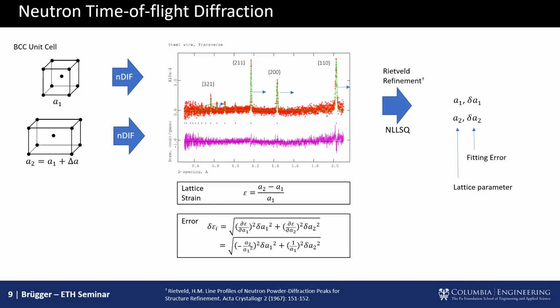Because the slip mechanisms and dislocation mechanisms of plastic deformation are entirely different from your elastic strain behavior, you're blind to the plastic side, but because of that you can fully deconvolute the system if you have, for example, another surface measurement. You can use videogrammetry, you can use DIC or just traditional strain gauge grids. Then you can get the full strain on the surface. You can get the elastic strain on the surface with neutrons, but then you can also get the elastic strains inside the body of the system.